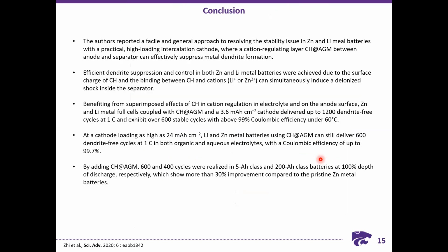So in conclusion, the authors have reported a general approach to resolve the stability issue which is present in zinc and lithium metal batteries, in a quite practical and scalable way, using a cation regulating layer, which is the collagen hydrolysate coated on AGM between the anode and the separator to suppress metal dendrite formation. So it can be concluded that efficient dendrite suppression and control can be achieved by guiding the cations with the use of charged biomolecules.